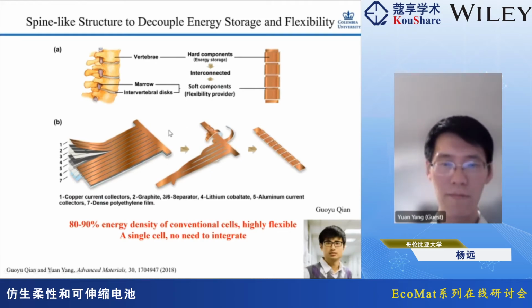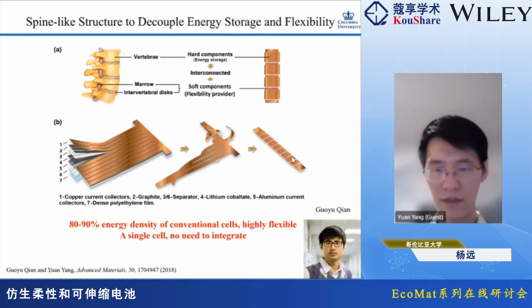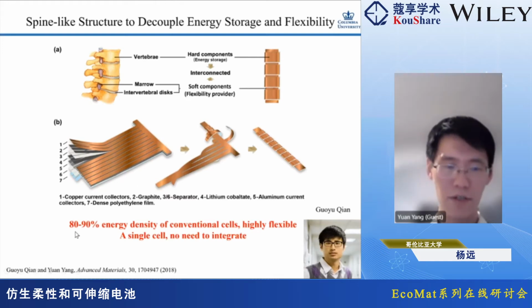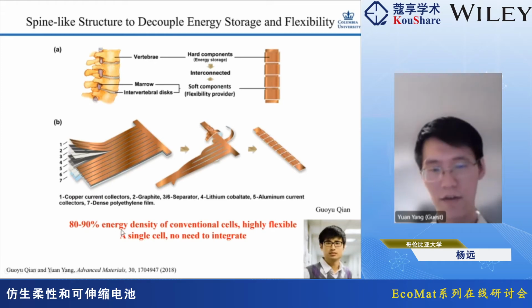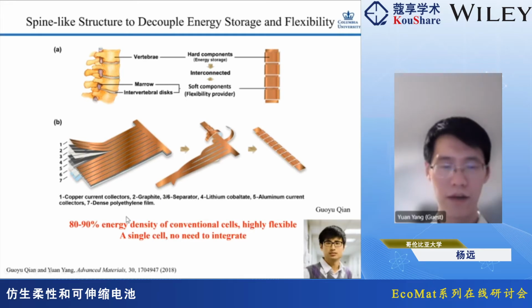To make such spine-like structures, we first cut the electrode and separator into a brush-like structure. Then we wrap the teeth onto the backbones, so that we finally form a spine-like structure. In theory, the system can reach about 80 to 90% of the energy density of conventional cells and be highly flexible. It's also a single cell, so there's no need to integrate many small cells together, which makes the whole process simpler.